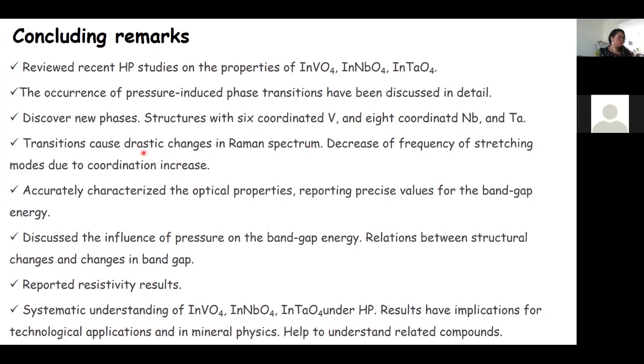The transition caused important changes in the Raman spectrum, in particular a decrease in the frequency of the stretching modes, which are the internal modes of the vanadate, niobate, or tantalate units. These changes of frequencies are related to the coordination increase, and we have accurately characterized the optical properties. I think we have solved all discrepancies available in the literature about the value of the band gap at ambient pressure, but we have also characterized it under high pressure. I discussed the influence of pressure on the band gap energy and established relations between the changes in the crystal structure, in particular in the coordination of atoms, and the collapse of the band gap. I reported resistivity results, and they corroborate the results from the optical absorption studies.